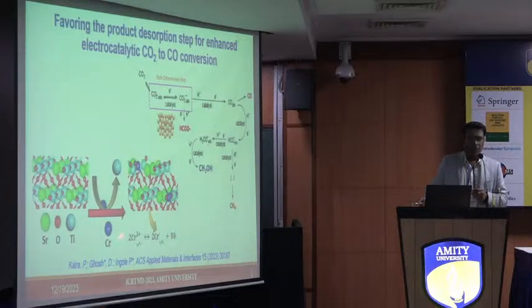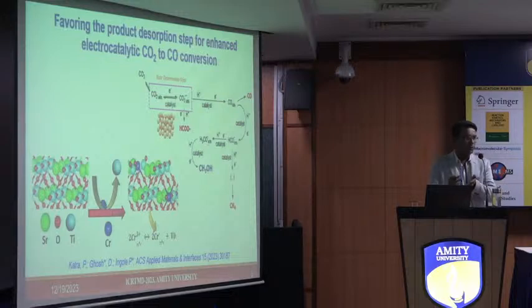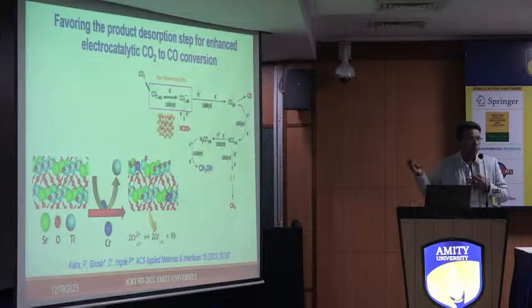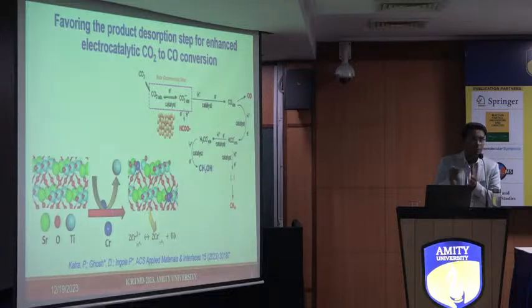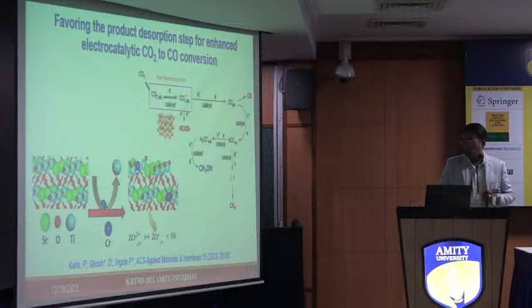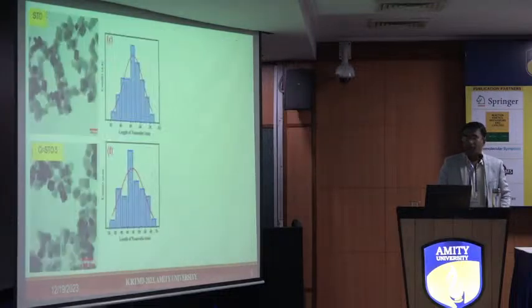When it is replacing the titanium, it is doing two things. One, it's creating more oxygen vacancies, which we need for more adsorption. Second, it is also changing the charge dynamics. If you look at the Bader charges, I'm going to show it. It changes the dynamics of the electronic environment of the oxygen vacancies which are already present there. Okay, these are the two things that we are going to address.